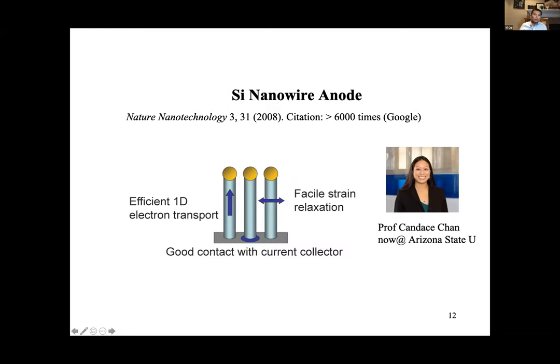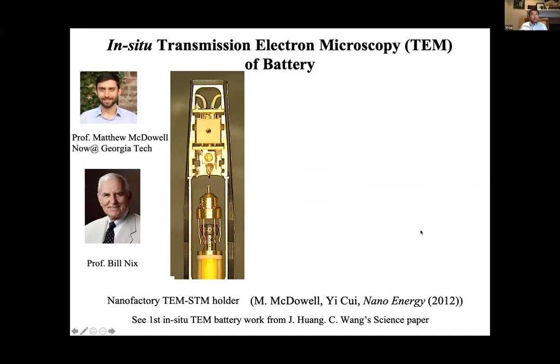This SEI layer needs to be stable with the volume expansion. Once lithium comes in and then goes out, the volume shrinks — this process makes the interface unstable. If it is moving mechanically and dimensionally all the time, it is very hard to build a stable solid electrolyte interface, and the battery fades very fast. Back in 2008, we published the first paper using silicon nanostructures in the form of nanowires grown from the current collector, which we recognized as the ideal structure to maintain electrical contact while relaxing strain without breaking.